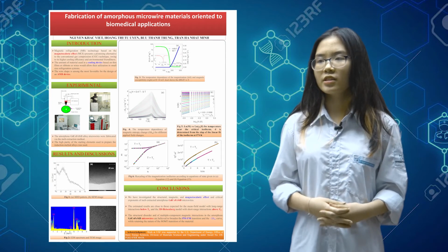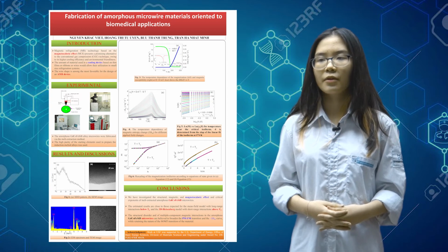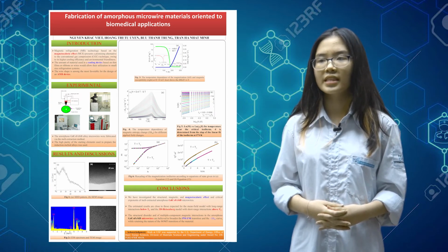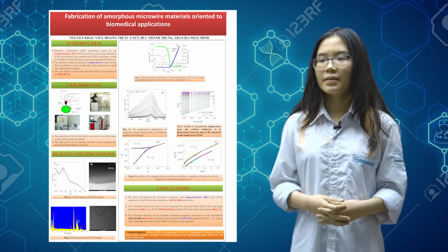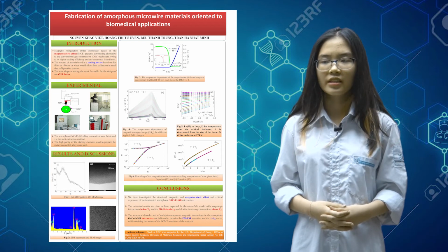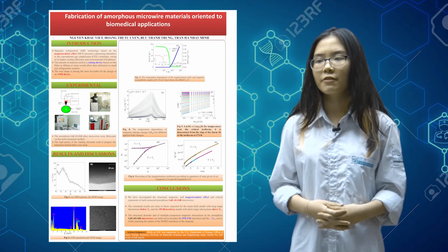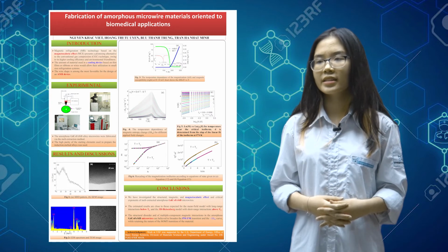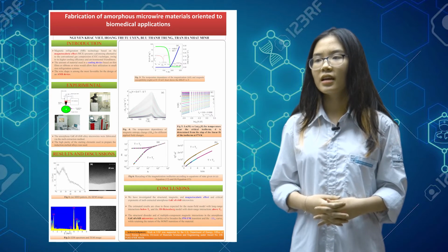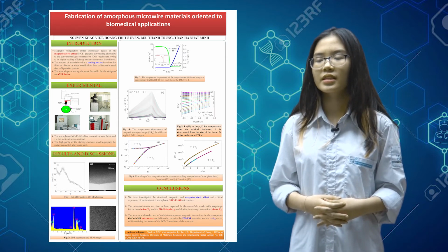Figure 3 shows the temperature dependence of the magnetization, left, and magnetic susceptibility, right, at H equals 10 millitesla. The inset shows dM/dT versus temperature. The temperature dependence of the magnetization M(T) for all specimens was measured while cooling under a DC field of 10 millitesla. Clearly, the sample shows a paramagnetic to ferromagnetic phase transition at Tc about 172 K, defined as the inflection point of dM/dT versus temperature.